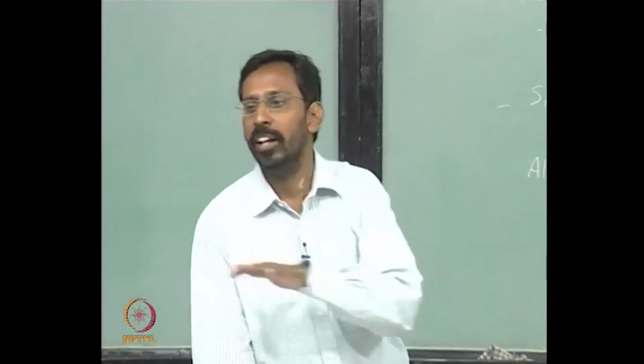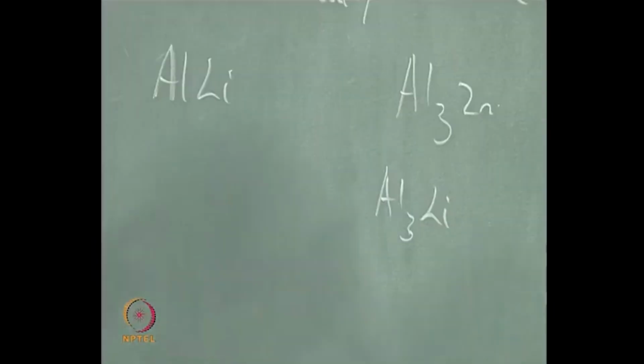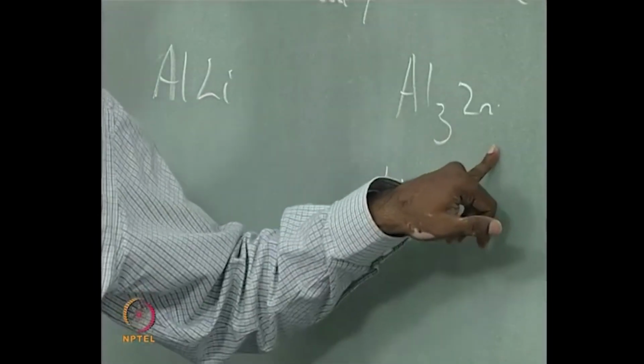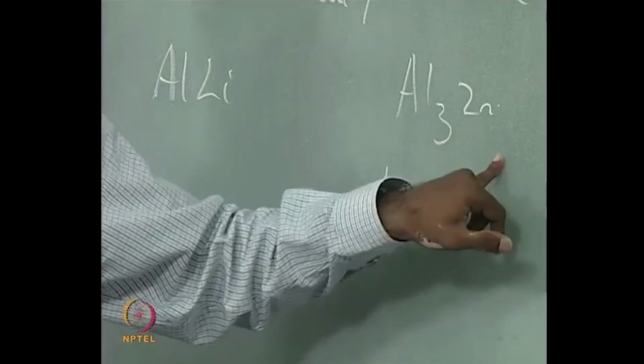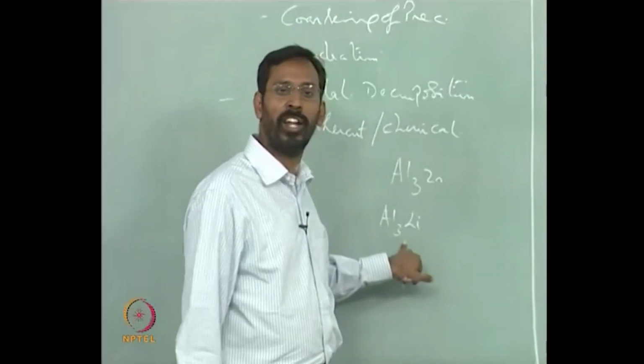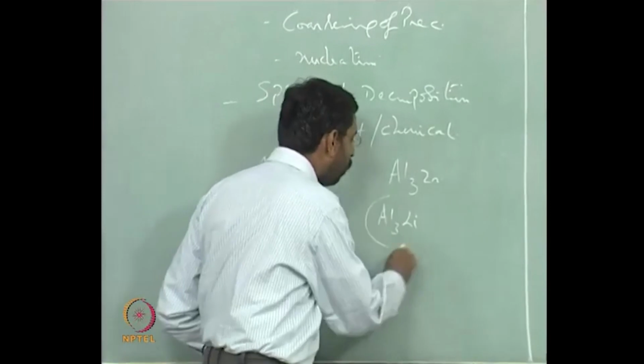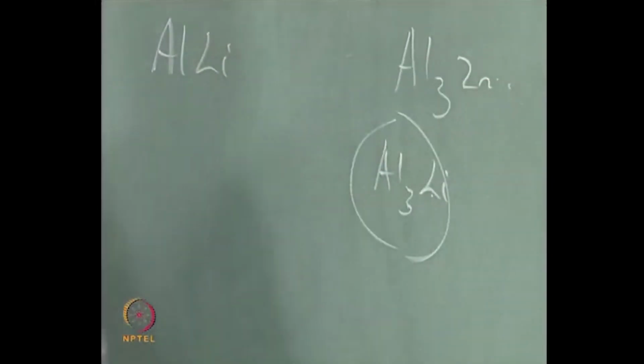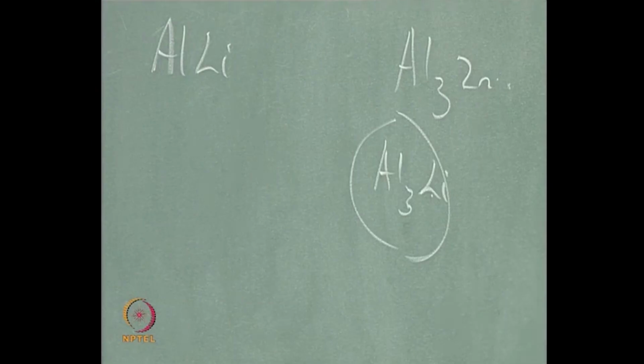And once you have that kind of a situation, you would see this planar slip or the slip localization becomes difficult, because in Al3Zr the bond between aluminum and zirconium is much stronger there. The ordering energy here is much stronger than the ordering energy here. First of all, this is a metastable phase, whereas this is not a metastable phase. In fact, how do I know about the ordering energy?